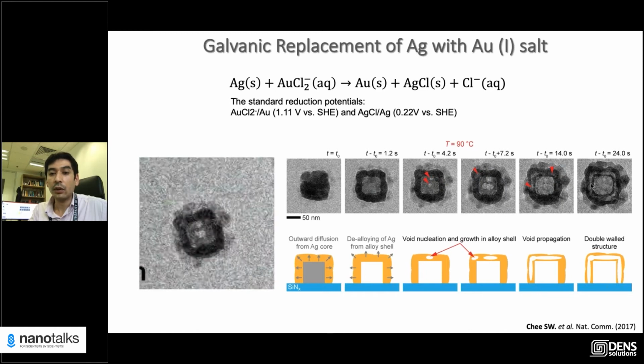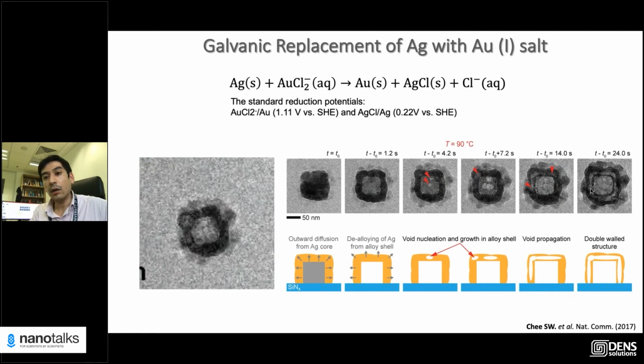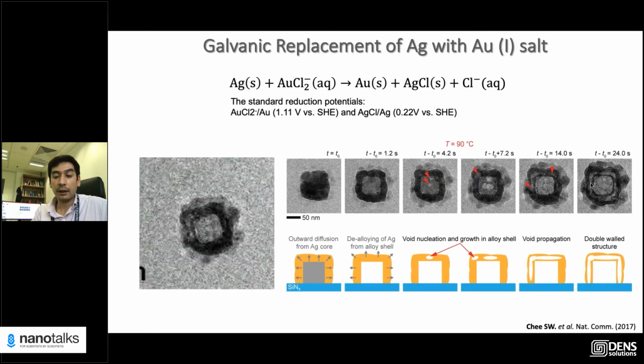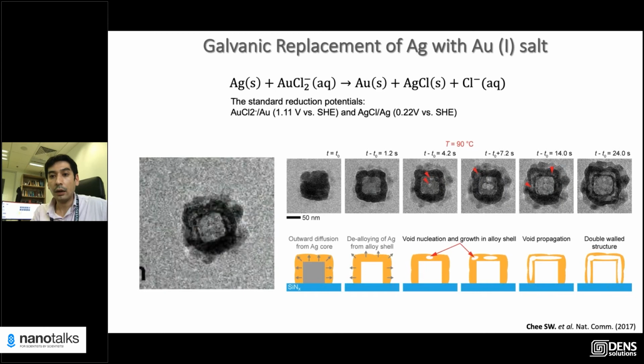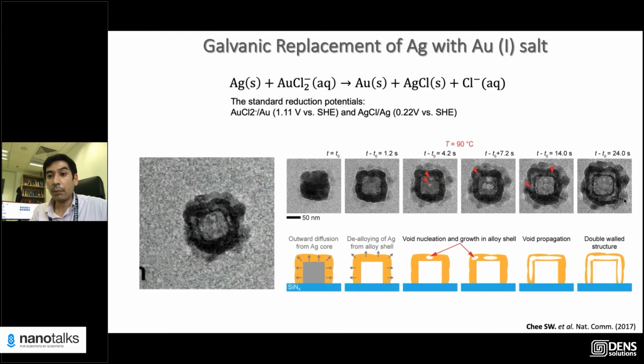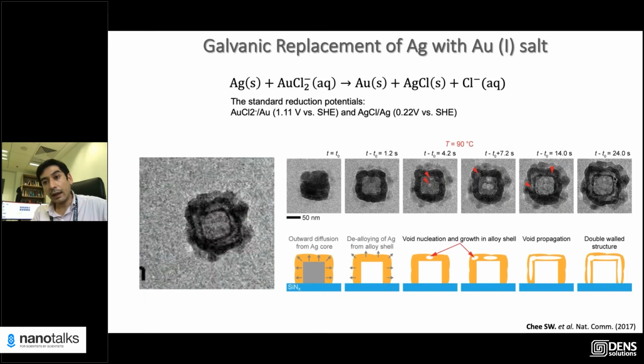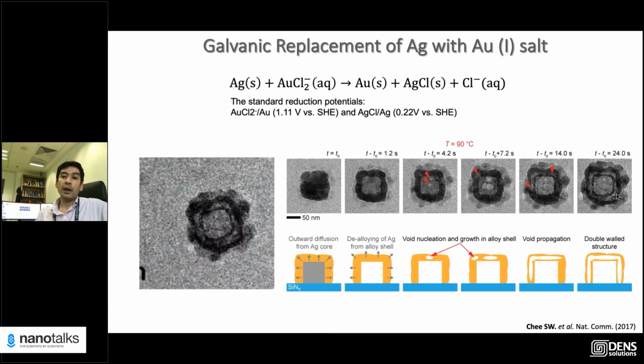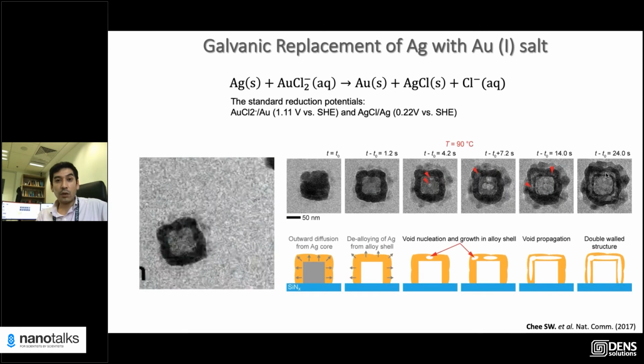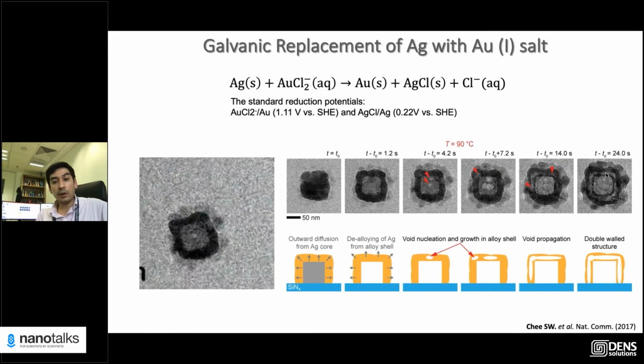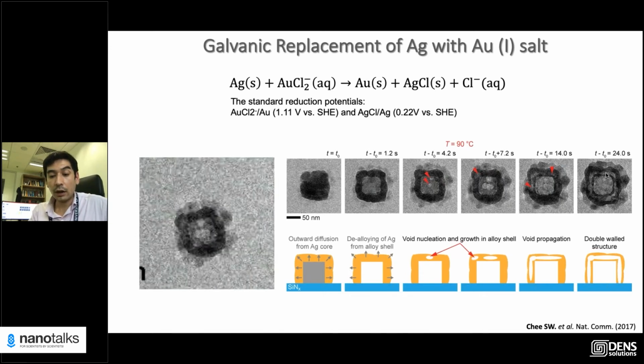for this interlayer, right? So you have this gold. You have a gold-silver alloy. Of course, there is also some chlorine involved there, but nevertheless, a new layer that deposits now acts as another layer which hollows this layer. So you can really create double shell structures just by tuning the diffusion or the reaction rates. Okay, so I think I told you how we can really control these nanoparticle architectures, right? So by growth, by annealing, or by etching.